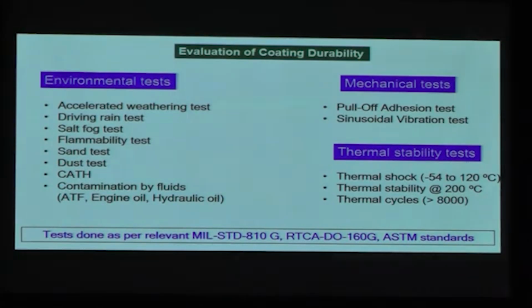Further to this, the coatings were also tested for their mechanical durability. So they were tested for their intactness under vibration test and also pull-off adhesion test. Adhesion is a very, very important factor for these coatings on the aircraft to have a long service life. So in the next slide, I shall detail you a little on that. Further, the coatings were also highly stable against thermal tests which were carried out, including thermal shock, thermal stability and thermal cycles up to greater than 8,000 cycles.